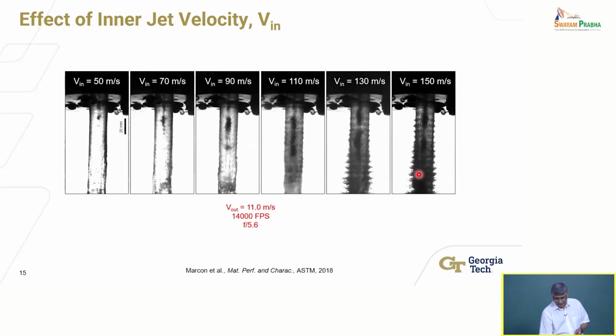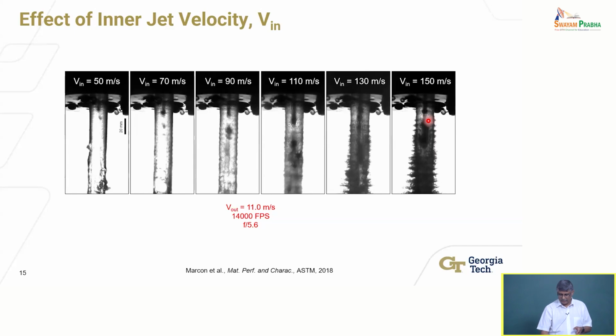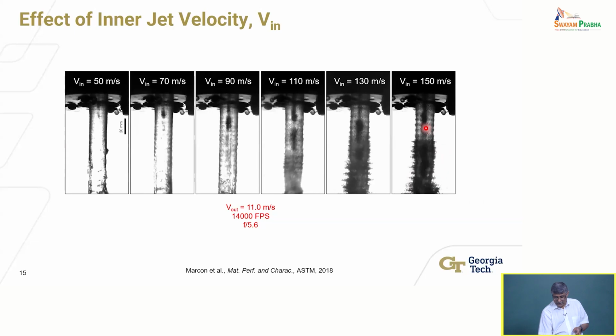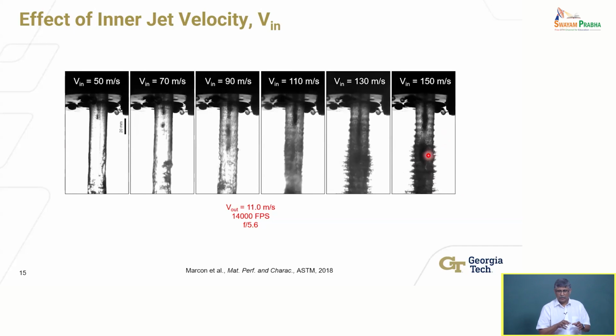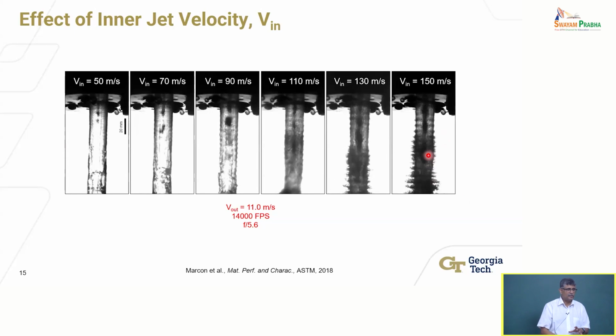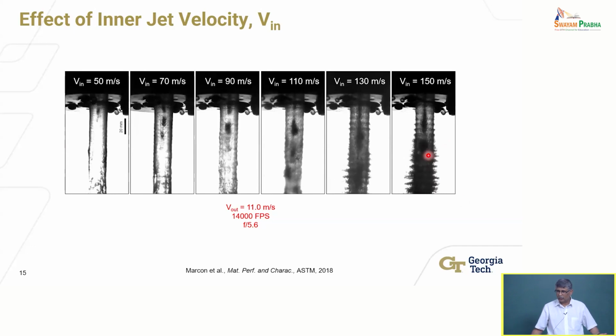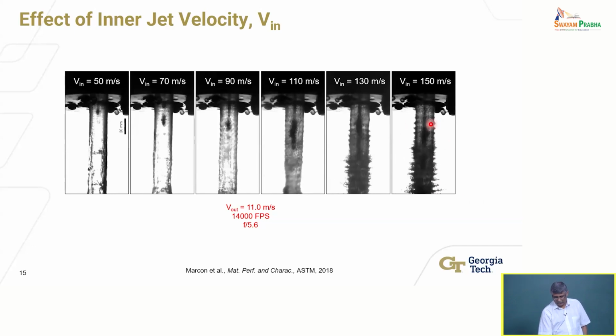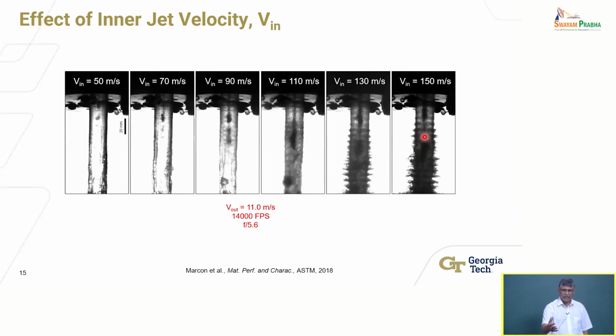Of course, this is the greatest. If I go beyond this, I may be able to. We had limits with our system, but you can see here, as you go from here to here, there is greater disruption of the flow. You can't go too far out. You can't put your surface here because already this entire flow is dissipating. You know, what is happening is that the inner jet is accelerating the outer jet, right? Because the inner jet is moving at 150 meters per second, the outer jet is moving at 11 meters per second, accelerating it, and eventually it destroys the flow characteristics. So yes, I can generate very thick clouds of cavitation, but then the distance to which that cavitation cloud can be carried by the flow is limited. Okay, that's what it means.